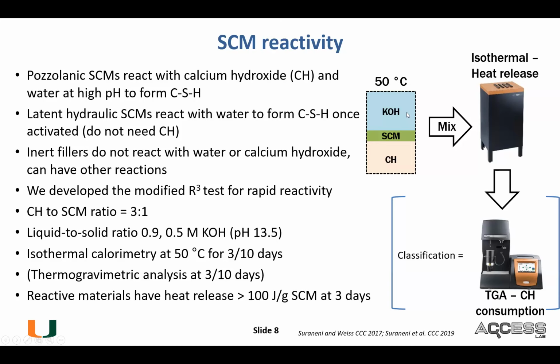And then the second category is latent hydraulic SCMs. These are typically calcium-rich materials. They're disordered enough or reactive enough in terms of the phases they have that they actually react directly with water to form calcium silicate hydrate. At high pH, they do not need CH. CH is calcium hydroxide. They can react with the calcium hydroxide, but they don't need it.